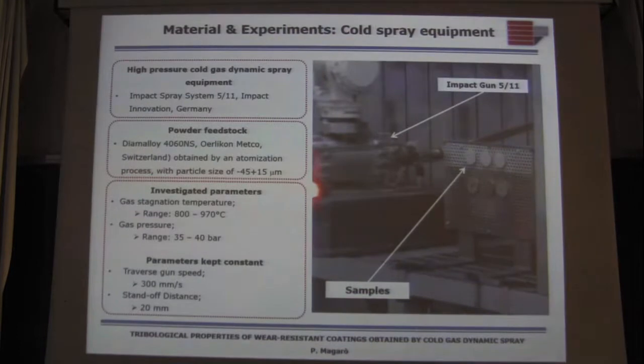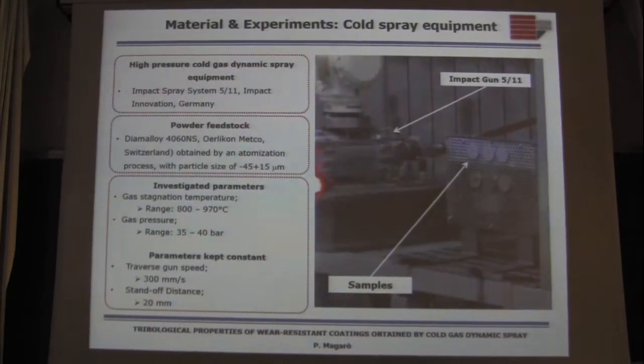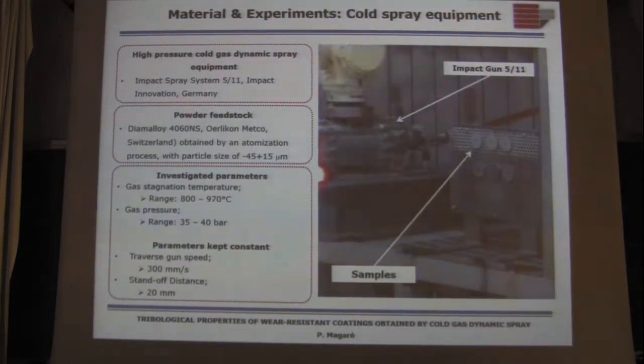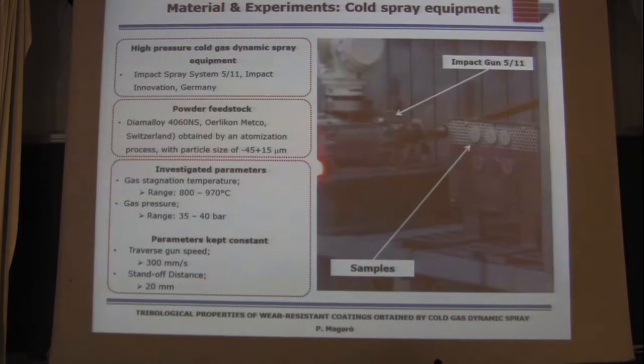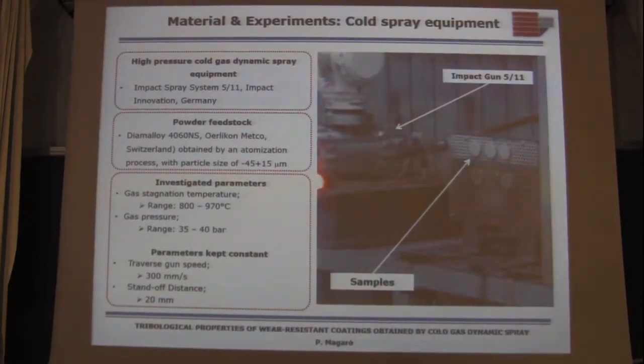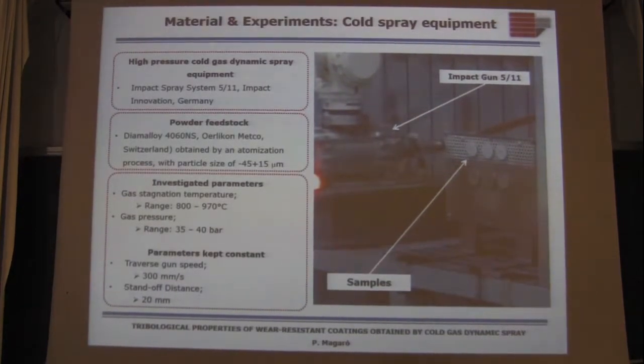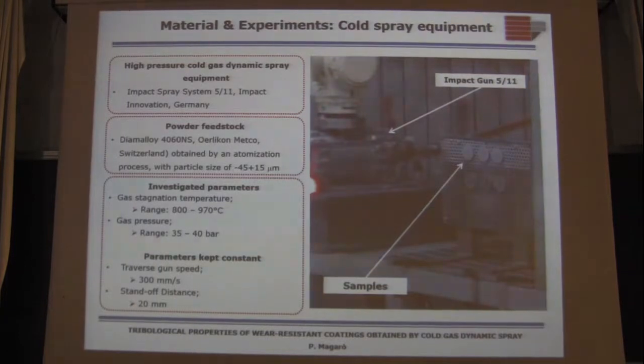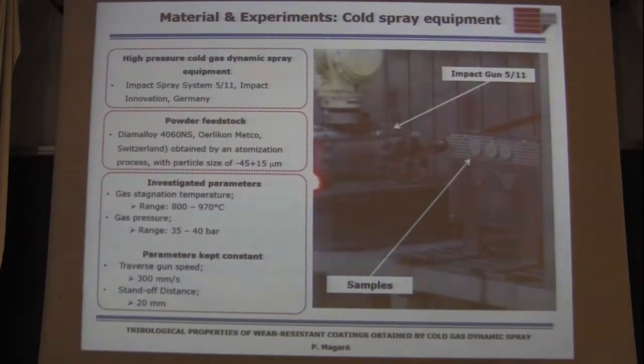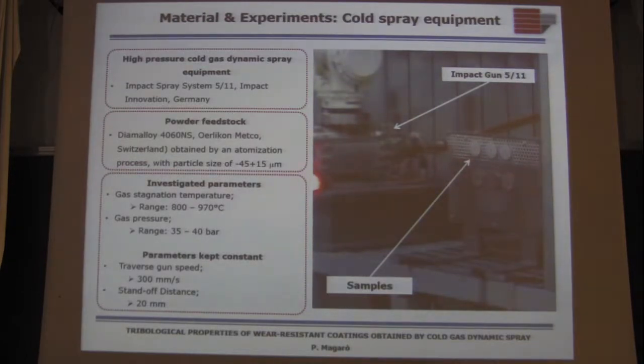The high-pressure cold gas dynamic spray equipment was an Impact Spray System 5/11 by Impact Innovations, and a commercial Diamalloy 4060NS powder with a particle size of around 40 microns was used. At first, the thermomechanical parameters were investigated, in particular the gas stagnation temperature in the range of 800 to 970 degrees, and gas pressure in the range of 35 to 40. The other mechanical parameters were kept constant, in particular traverse speed equal to 300 millimeters per second, and the standoff distance equal to 20 millimeters.